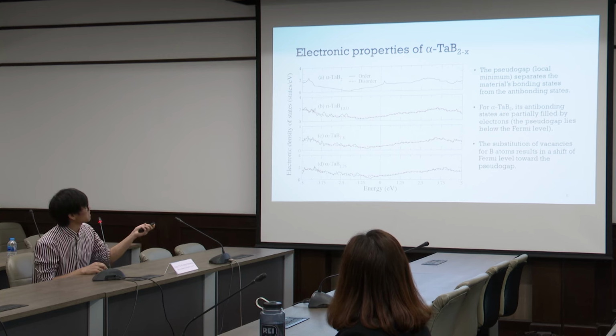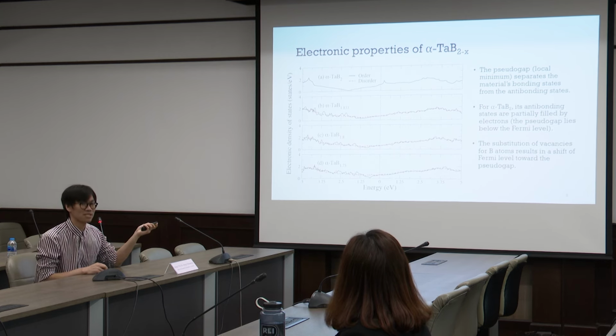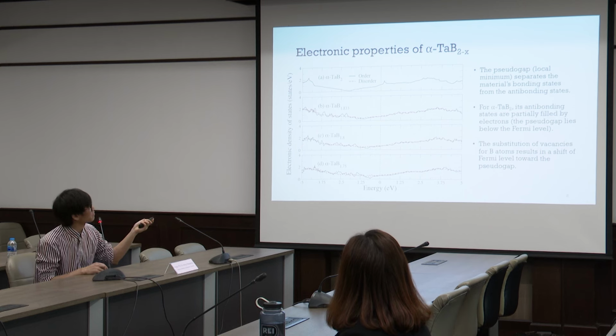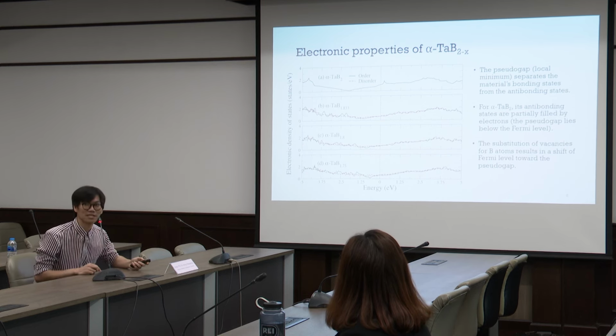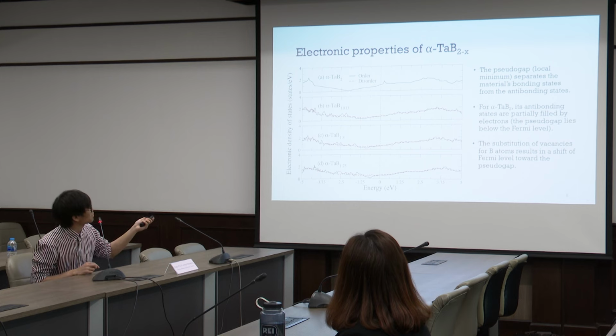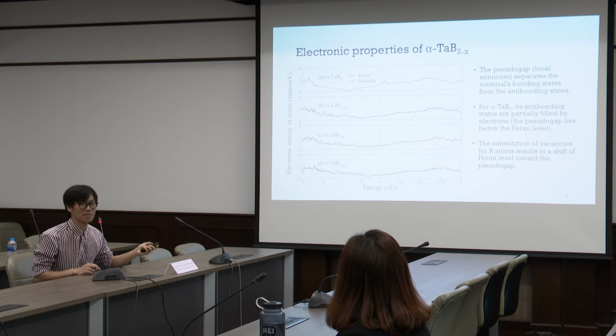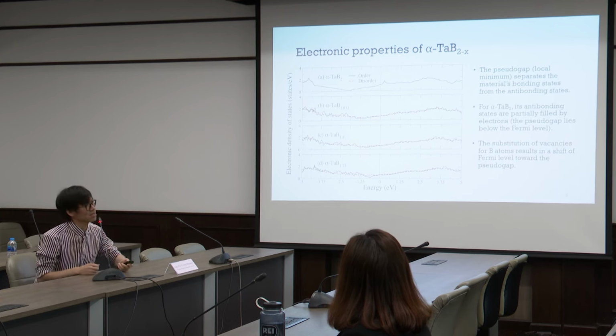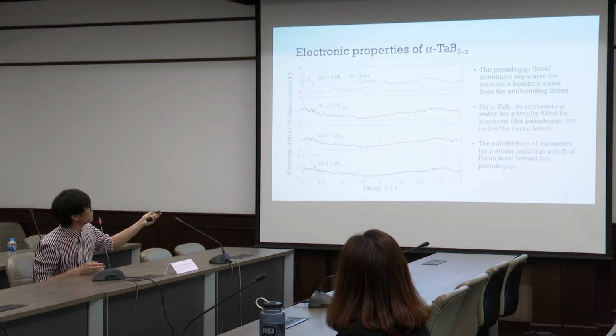The reason can be explained by the electronic band filling effect, or the change in the electronic property of this compound. This figure shows the electronic density of states for TaB2, and you can see the local minimum in the density of states. This point is called the pseudo gap, and it separates the bonding and anti-bonding states of this material system. The states with energy below the pseudo gap are the bonding states, and those to the right of the pseudo gap are the anti-bonding states.